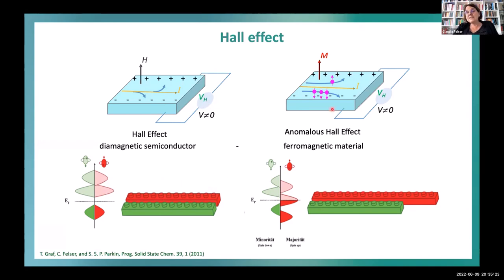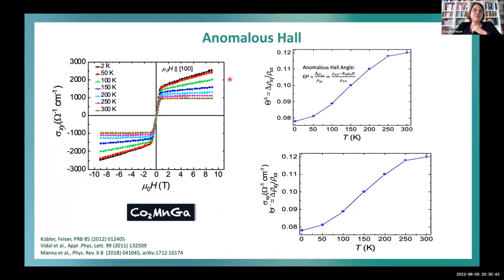So if you have intrinsic magnetism, and this was the idea of Haldane, the quantum anomalous Hall effect, we have an anomalous contribution to the Hall. So we don't need this external field because the magnetization is already there. So we can measure the anomalous Hall contribution, which is what we see in ferromagnetic material. And then the curve looks like this.